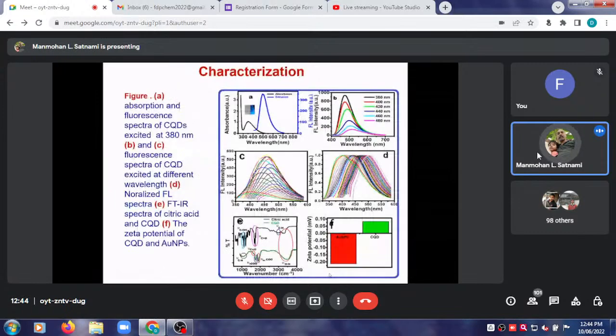Okay, so you can see from here the carbon quantum dot we prepared. It looks bluish under the UV light, and it gives absorption spectra maximum at 355, and emission at around 470, not 500. And this carbon quantum dot gives fluorescence excitation dependent emission. You can see, as the excitation wavelength is increasing, the fluorescence spectra is shifting and intensity is decreasing.